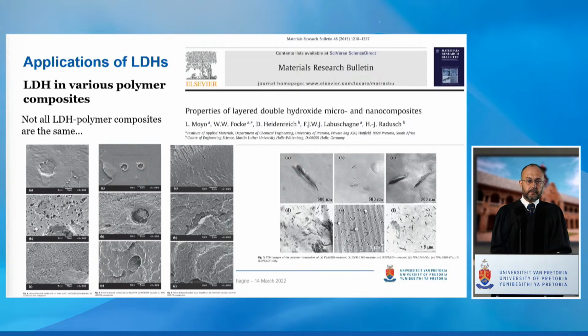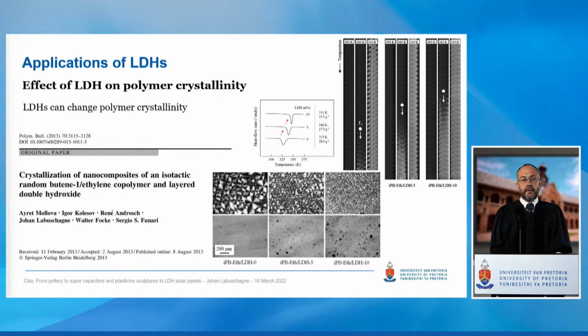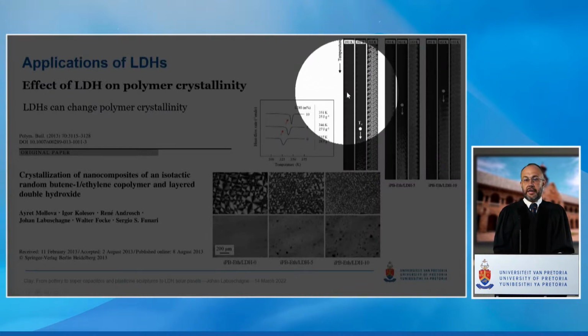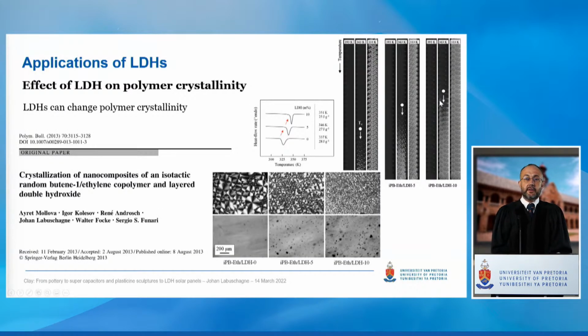In this publication, we show the effect of the clay loading on crystallinity. Right-hand top corner, you can see three different loadings. The first one is no clay, 5% clay, and 10% clay. We run down with temperature, and as we run with temperature for the different loadings, you can see that the crystallinity is changed. The material crystallizes more with an added clay. This also changes the mechanical properties. Typically, crystalline polymers are tougher and stiffer than non-crystalline polymers, although they can become ductile if too crystalline in the end.